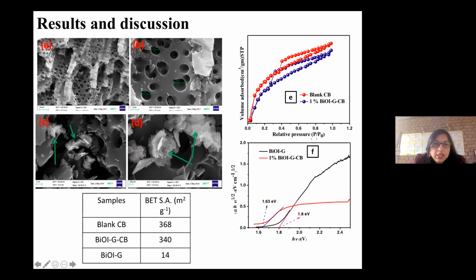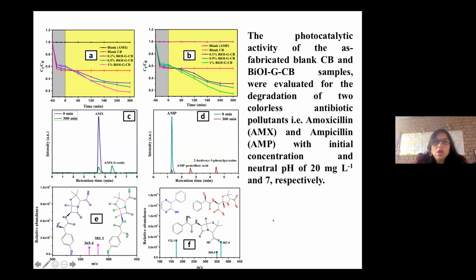You can see the blank carbon block, the surface area is 368, but when immobilized, the surface area decreased to 340. So now the blank carbon block and this BiOI GCB: this is the surface area and this is the band gap. The band gap of BiOI G, you can see, is 1.8 electron volt, but the immobilized one shows 1.63 electron volt.